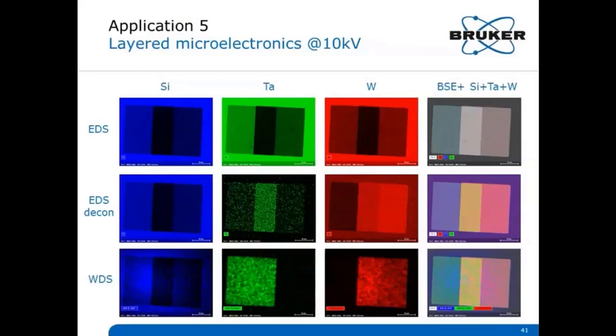Here we see the results of WDS mapping. WDS shows the correct distribution. Tungsten makes up the layer to the right, whereas tantalum makes up the layer to the left, and silicon is found throughout the sample. But it's more evident where the layers are not shading the substrate.